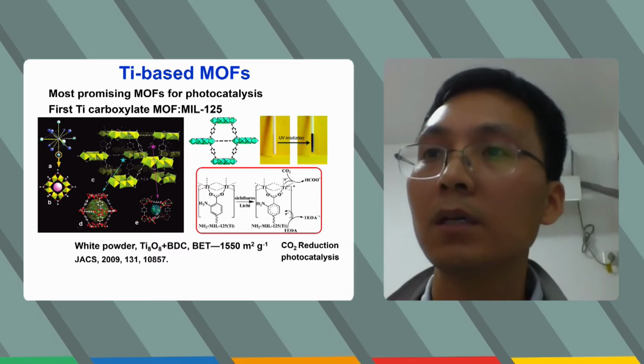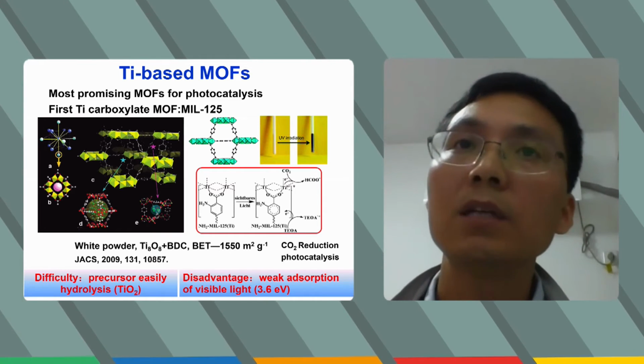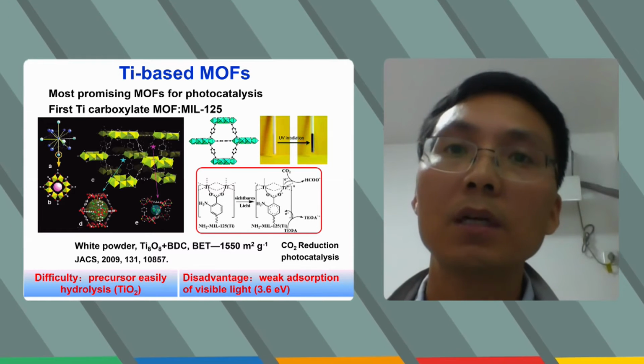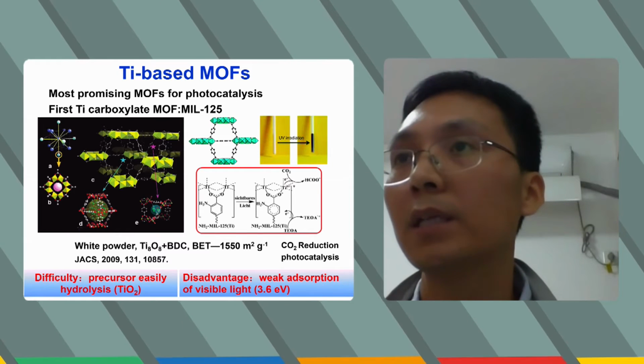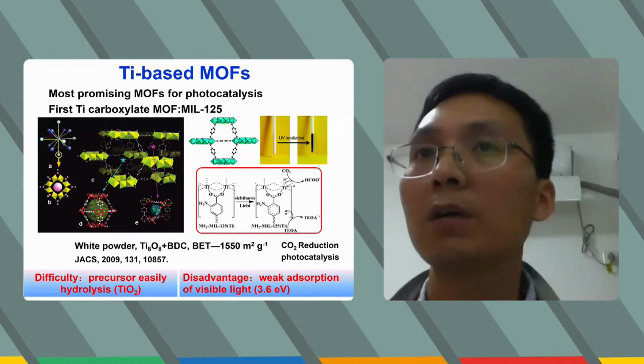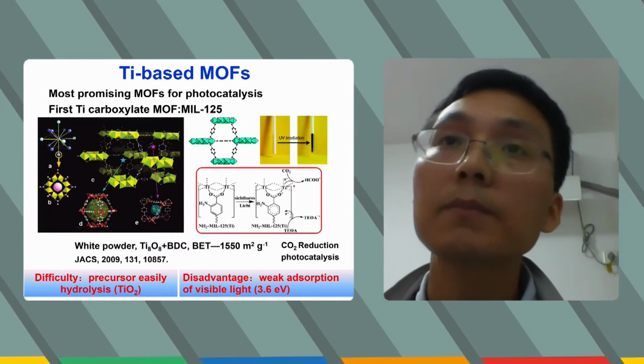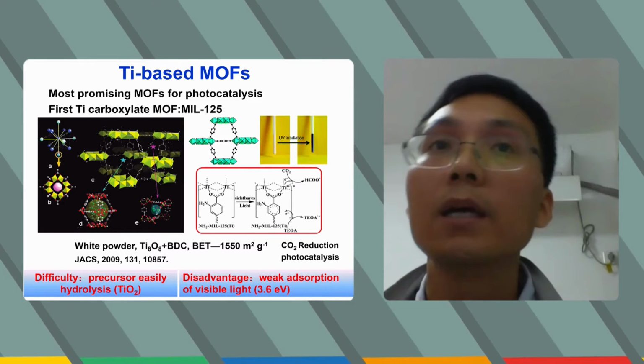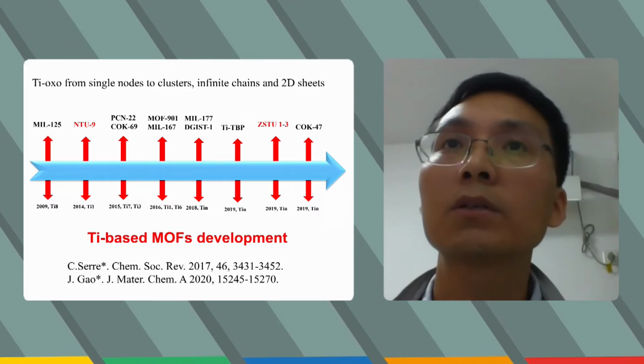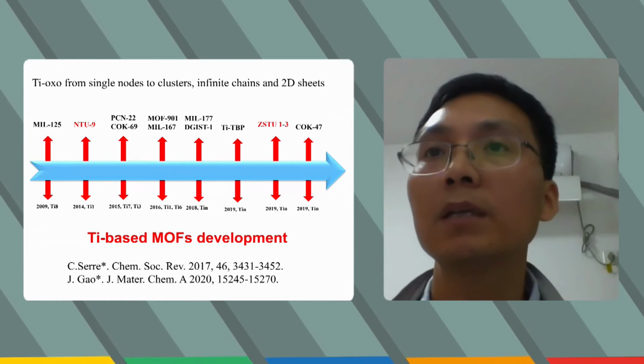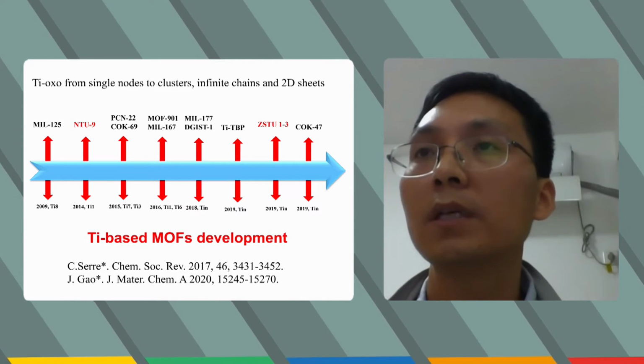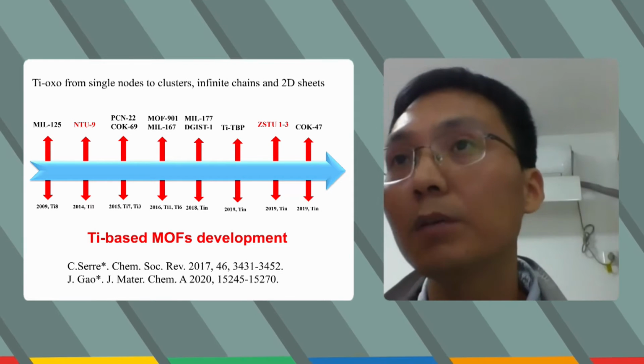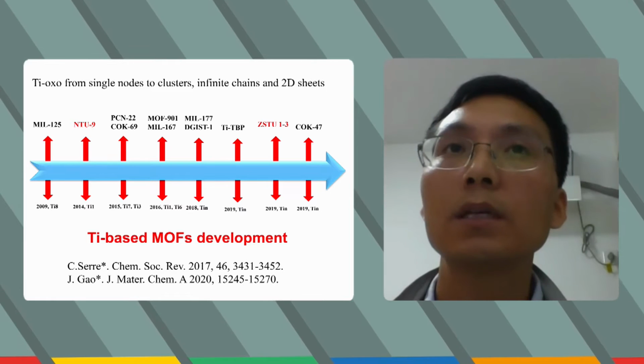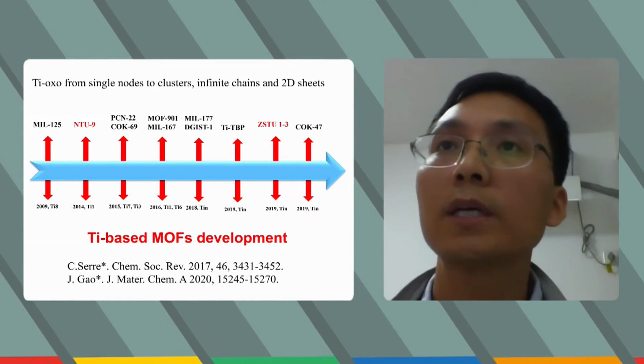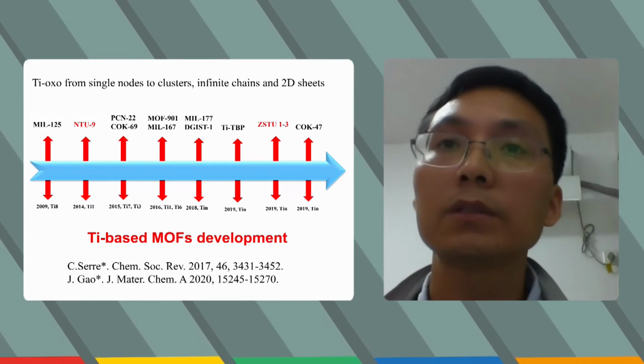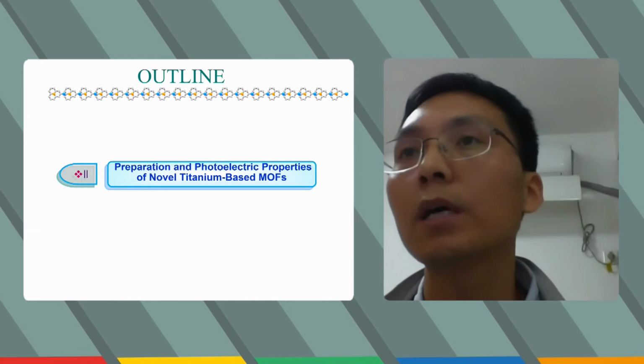This is its disadvantage. Also, titanium MOFs are very hard to synthesize because the precursors can be easily hydrolyzed into titanium oxide. So it's very hard to form titanium-based MOFs. In the last 10 years, titanium-based MOFs have been growing fast, but there are still limited numbers of MOFs in this area. I think there are still only about 20 MOFs. Also, the nodes in these MOFs range from single nodes to clusters, then to sheets. Next, I will introduce some of my works in these areas.